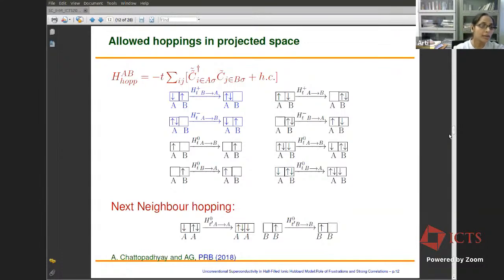So for example, we can still have a hopping from A to B sublattice, which creates a doublon on A sublattice and a hole on B sublattice, because a doublon on A sublattice and a hole on B sublattice are energetically allowed states. Similarly, we can have a reverse process where you start with a doublon on A sublattice and a hole on B sublattice, resulting in single occupancies on the two sublattices. So these nearest neighbor hopping processes are still allowed even in this strongly correlated limit of the half-filled Hubbard model.